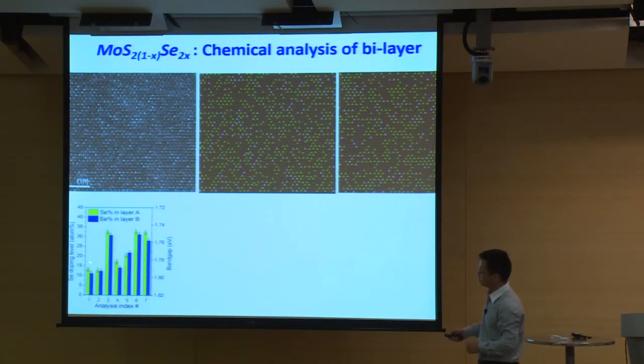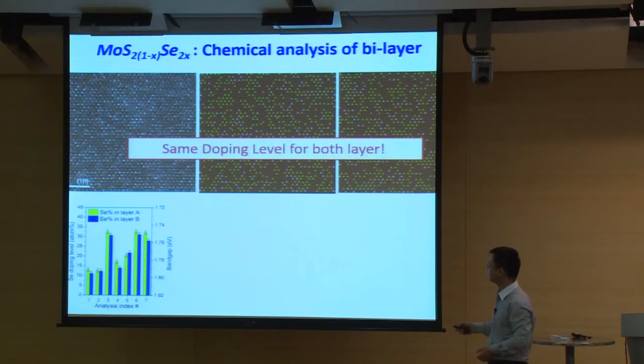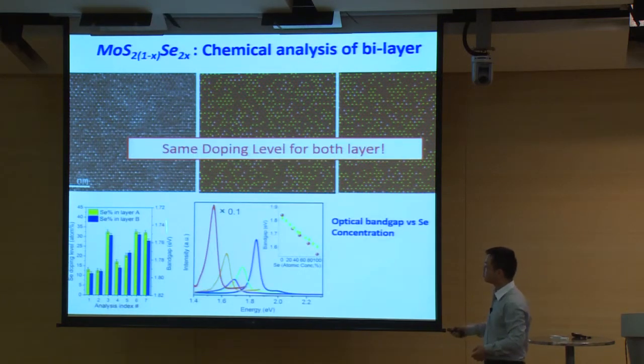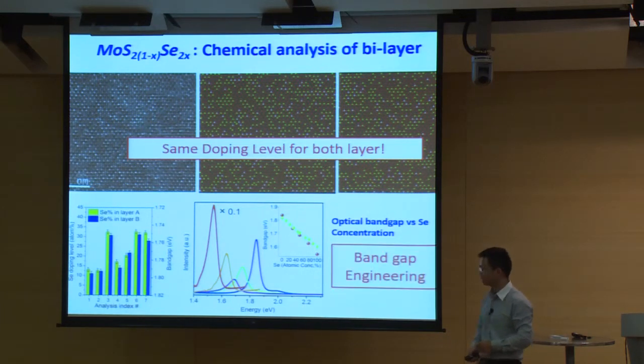And what's interesting is that for random sites, if we calculate the concentration of selenium for both layers, they're pretty close, which means the bilayer system may be simultaneously grown. And also, we can control the concentration of selenium from 0 to 100%, which means we can go from the pure moly disulfide to the pure moly diselenide. So this is the PL spectrum from 0% to 100% selenium. And the band gap can be changed from around 1.9 to below 1.6. So this is so-called band gap engineering.